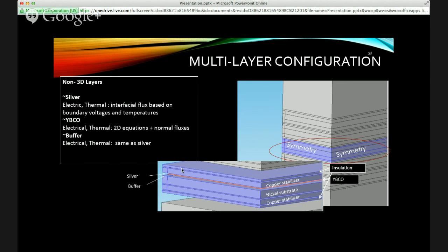So from there, I mentioned those five layers. Here they are, the five different layers of conductor, separated by insulation layers. If you look at the blowout view, that red area would be your YBCO, the 2D layer. Then you have the copper stabilizer above it, the nickel substrate, and then the copper stabilizer below the nickel substrate.